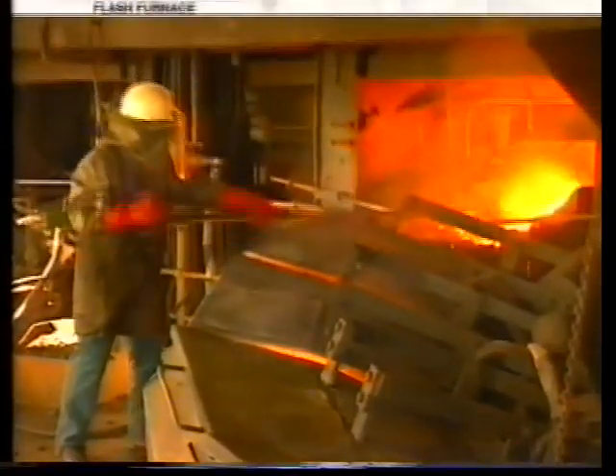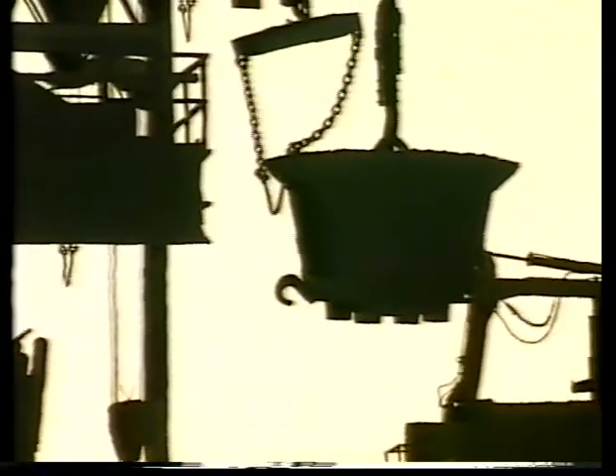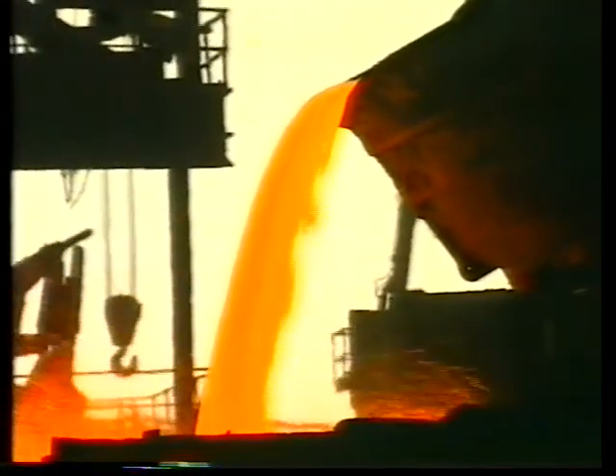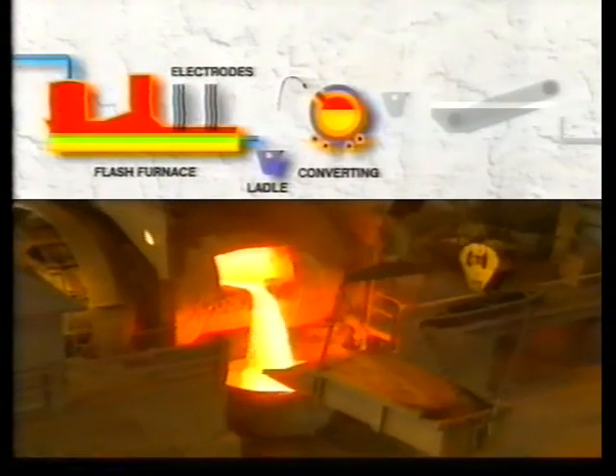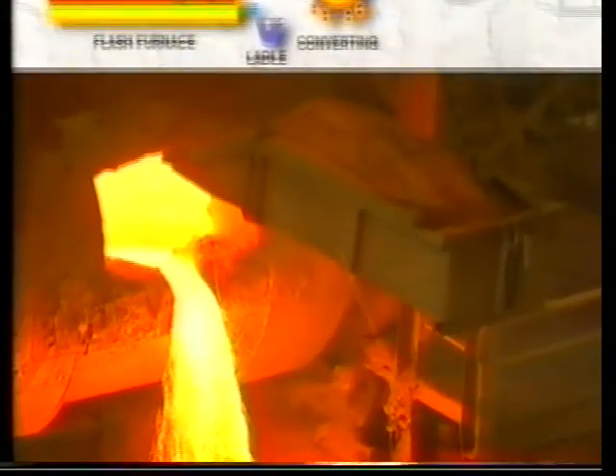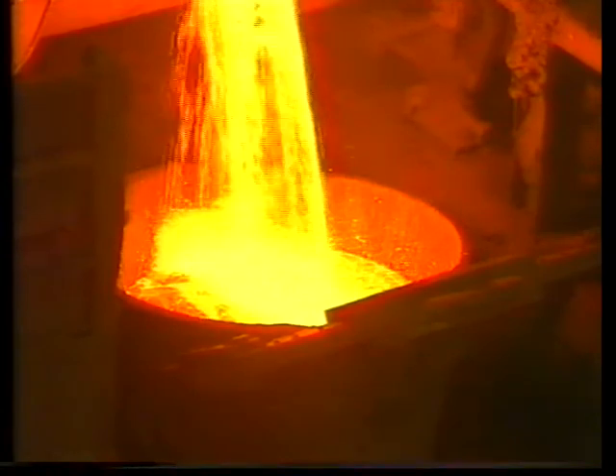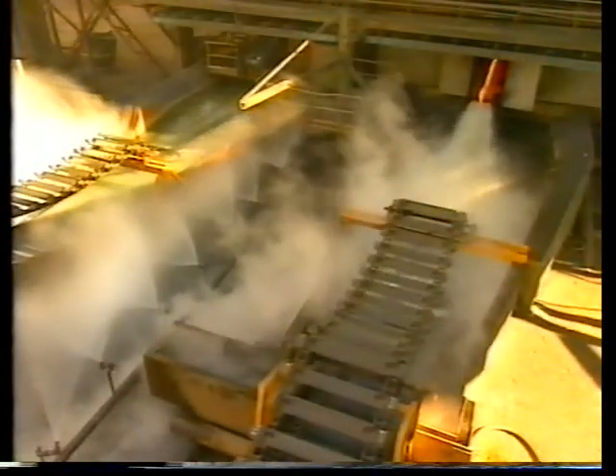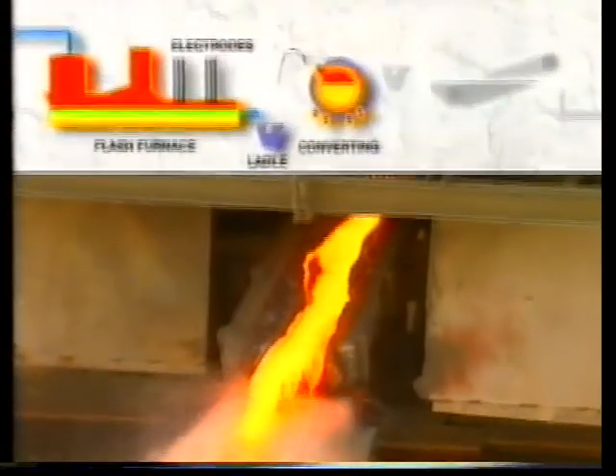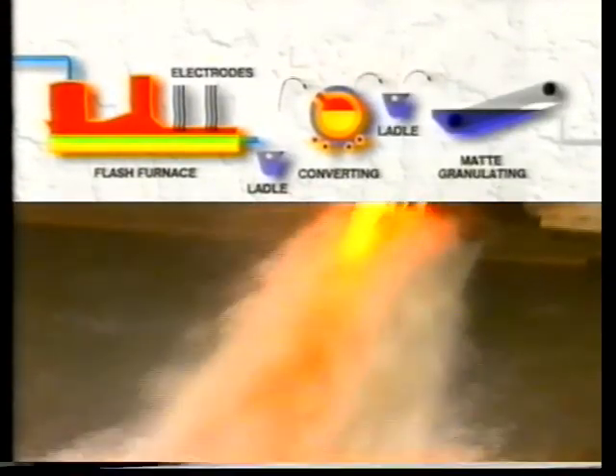The slag, or waste, which floats to the top is skimmed off and granulated for disposal, whilst the matte, now with a nickel content of around 44%, is poured off and transferred to nearby converters, where more flux is added and oxygen blasted through the mix to produce a high-grade granulated product containing about 72% nickel called nickel matte. Some of this high-grade matte is taken to a granulator and prepared for customers, while the rest is railed out to WMC's Kwinana refinery, south of Perth, for the next stage in the process, refining.